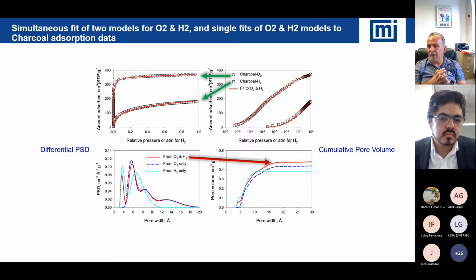So here, when you look at the red line that's going through the data points, it's a reasonably good approximation. You don't want to see unusual behavior in the fit. Unusual behavior with the fit will create gaps in the pore size distribution. And that was quite common early on with NLDFT, that for many materials, people would be reporting a pore size distribution, and there would be a gap and some absence of pores, and typically that was around 1 nanometer. So reporting the fit is absolutely critical.